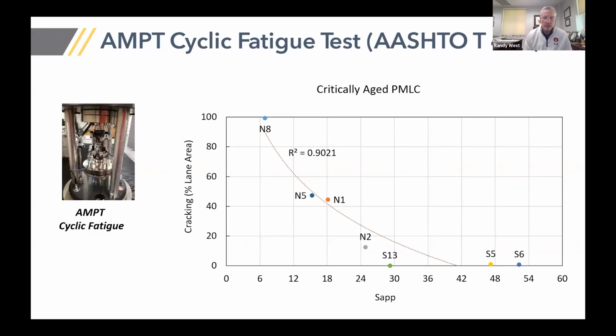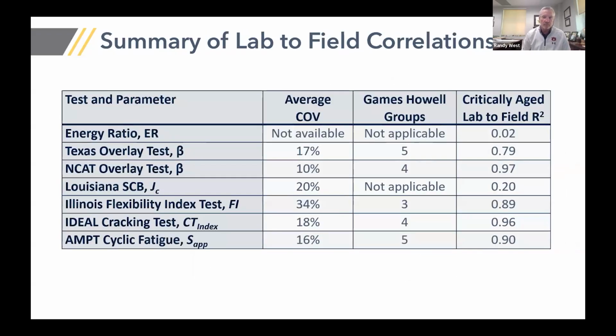So in summary, we have quite a few tests that actually correlated reasonably well between lab and field. Between the Texas overlay test at about 0.79, and the R squares up here at 0.96, anything near or above 0.8 is considered a really strong relationship. Now, some of these tests aren't simple. Some of these tests are not fast. So considering all those characteristics that I mentioned before, we certainly see why the IDEAL-CT test is popular. It has a reasonably good coefficient of variation, has a good statistical grouping, has a strong correlation to field performance.